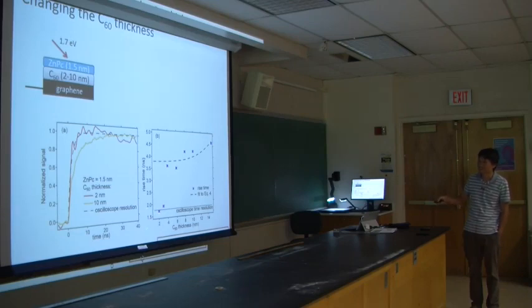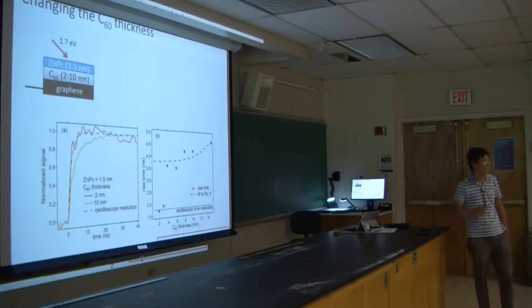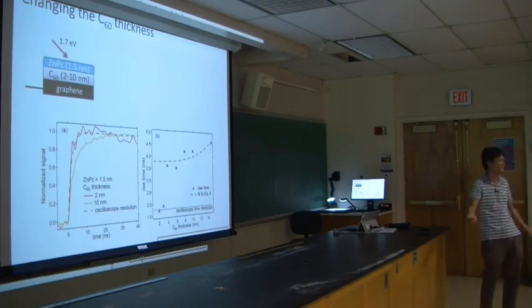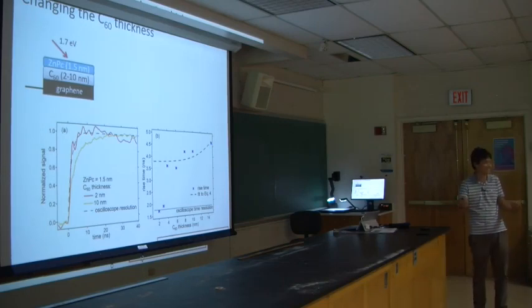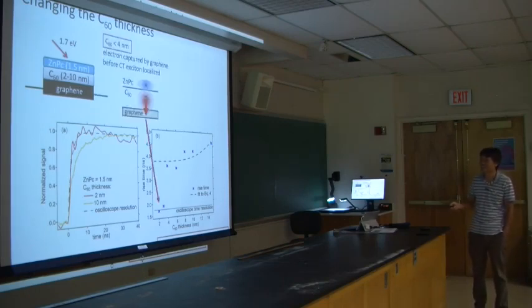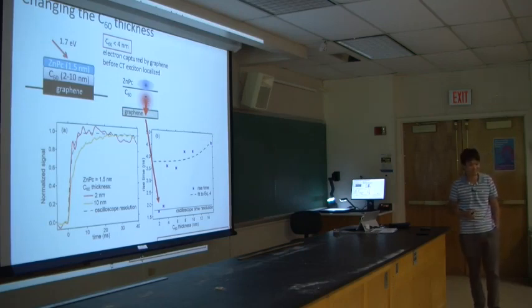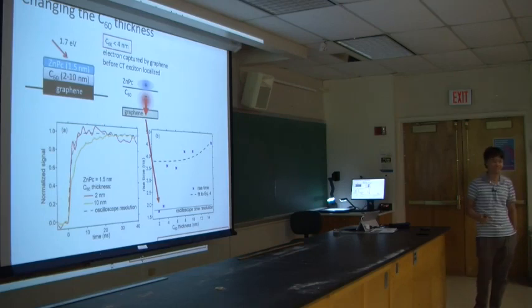But after we go to 5 or 6 nanometers, the rise time has a jump, from very fast to slower. Remember I said this hot CT state is about 4 nanometers? It seems to be related to that. What we think is happening is that for a very thin layer, we have this delocalized state, and the graphene pulls the electron out from this delocalized state before it has the chance to snap back to the hole. That's why you have this extremely efficient dissociation.